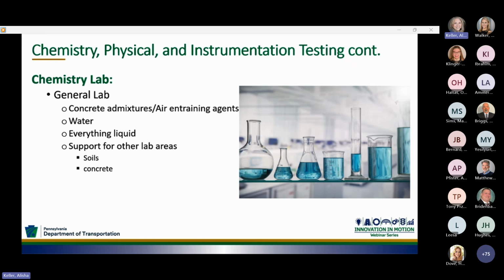In this lab, we receive from the districts concrete admixtures and air entraining agents for which we test for specific gravity. If there is a discrepancy with the specific gravity results, we obtain a fingerprint of what the product is supposed to look like by using infrared spectroscopy, where we look at the molecular structure of the product.